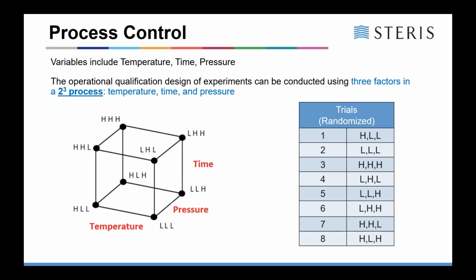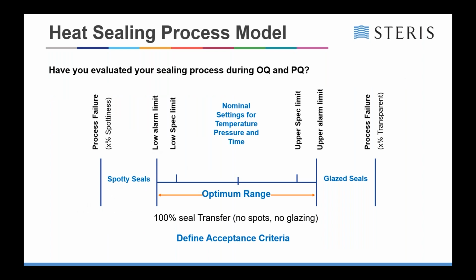So basically what you're doing is you're getting a set of samples that can be tested, and you're looking for the actual nominal setting for that particular pouch and those particular materials. And that's what you're looking for, that you're in the middle of that range.